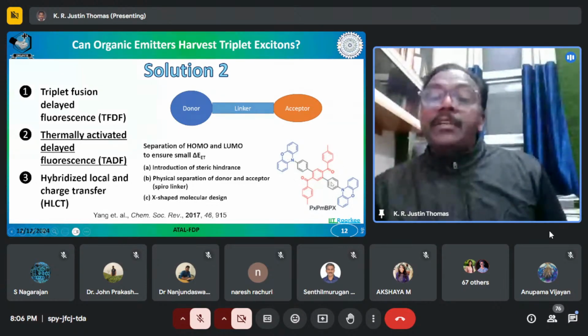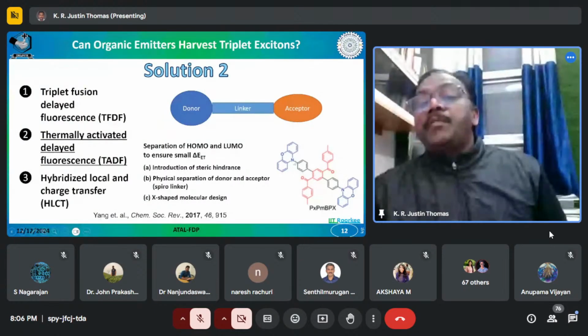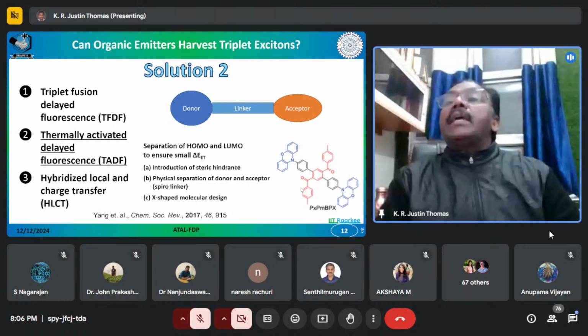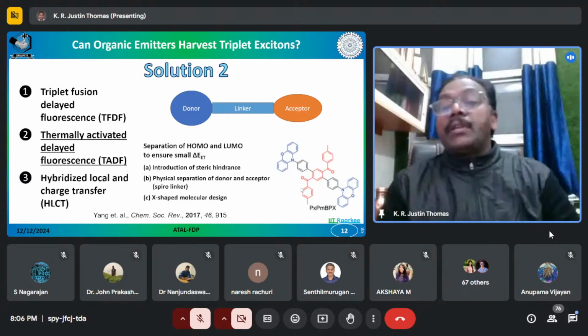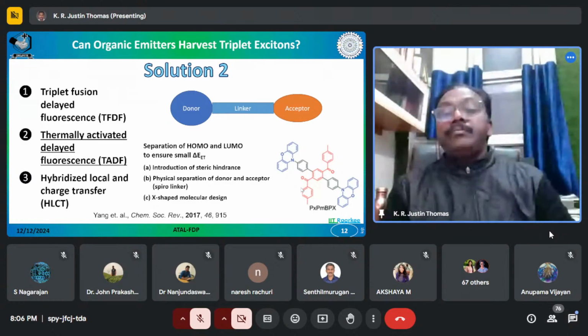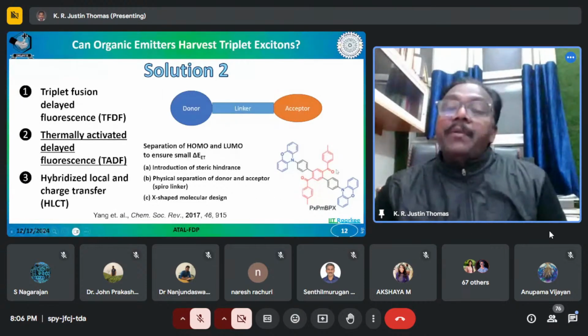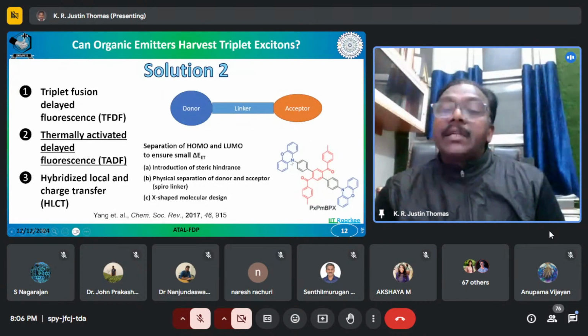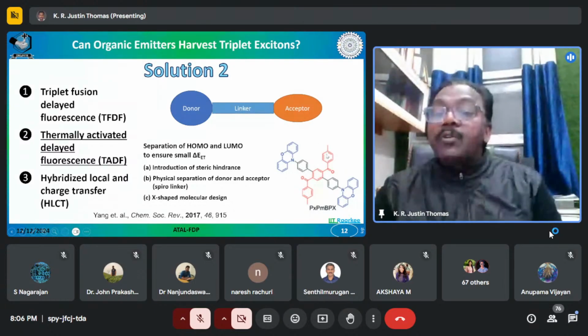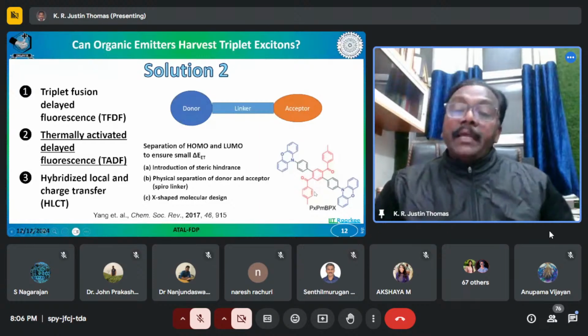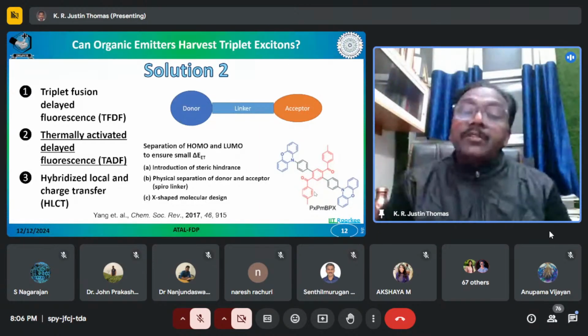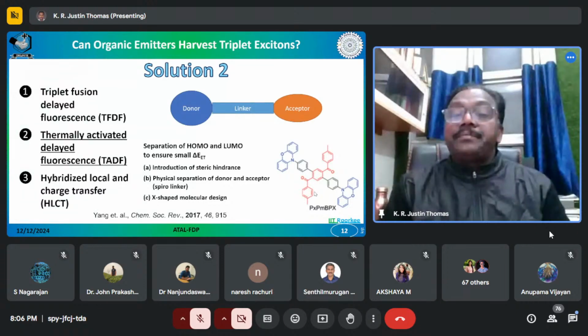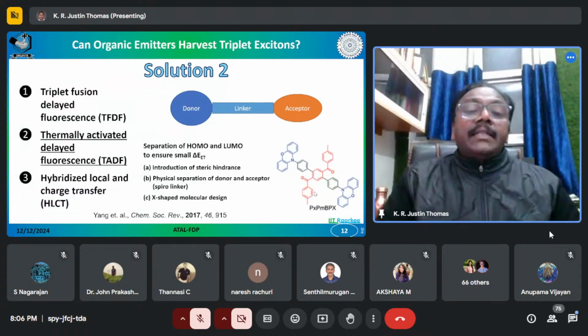and there is no effective interaction between these two axes. One can call this one a donor axis, this an acceptor axis. There is no effective electronic interaction between the donor and acceptor axis. So if you look at this molecule, the HOMO will be mainly localized on this axis, and the LUMO will be on this acceptor axis. There will be very poor overlap at this phenyl group for the HOMO and LUMO. Because of this aspect, these molecules will also show a small delta EST. So now these are the three classes of molecule.